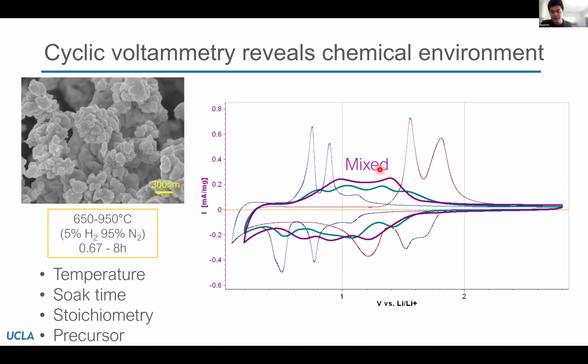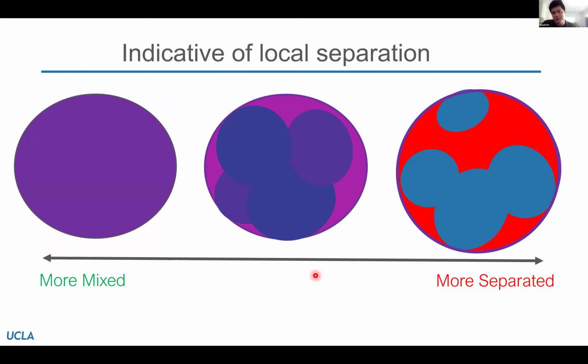versus when we make a more mixed solid solution, we can see that the redox reactions are in a more concentrated voltage range, and that there are less clearly defined peaks, which again would indicate that rather than having small domains that are enriched with molybdenum or enriched with tungsten, we've achieved better mixing, where there is a random distribution of each element. Okay, and so just to again visualize that, we're operating on a spectrum here, where even though, represented by this purple outline here, we can look at something through XRD and say that something is 1 molybdenum, 1 tungsten dioxide, what we can instead have is, at the nanoscale, a wide range of local mixings that can happen. And we'll see right now that that has an effect on phase transition behavior.